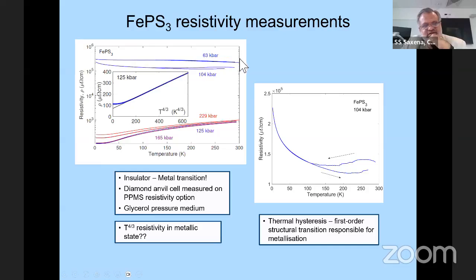So for FePS3, at starting pressures before the van der Waals collapse, you see that it's still pretty high resistivity. And then you cross over, at around 100 kilobar, from an insulator or bad metal to a metallic state, and the system becomes quite metallic. Two things to point out, there are many things here, but two to highlight. One thing is that the power law comes back to life again. So it's a magnetic insulator which becomes a magnetic metal, and a magnetic metal with no long range order. Sorry, it had long range order, long range antiferromagnetism, which under pressure gives way to a magnetic metal with short range fluctuation order, which shows up in resistivity.